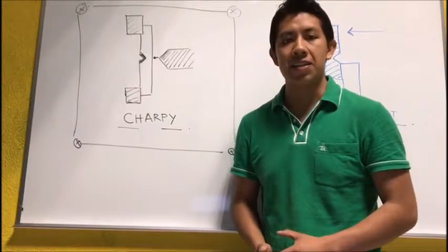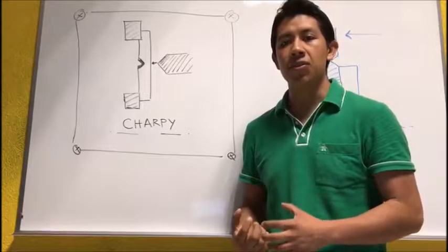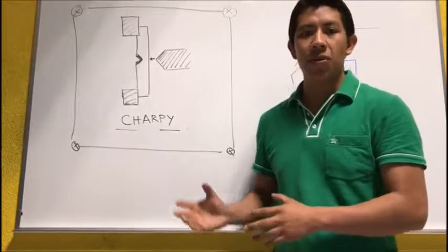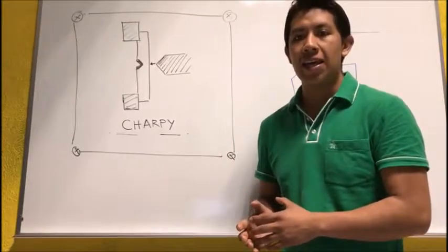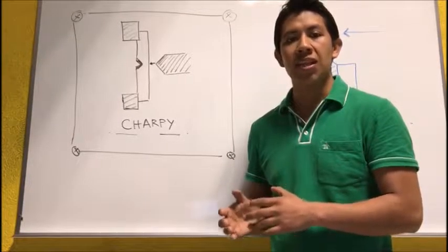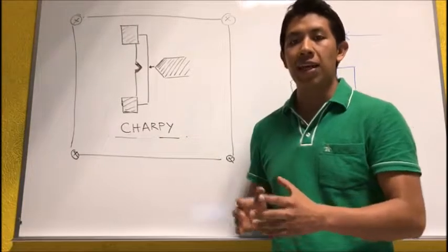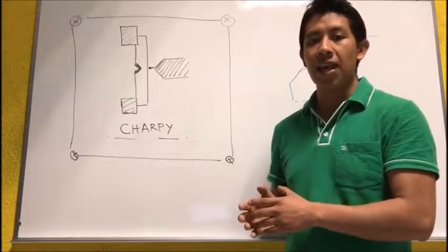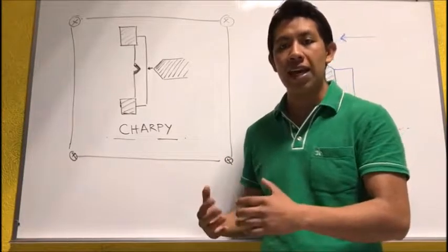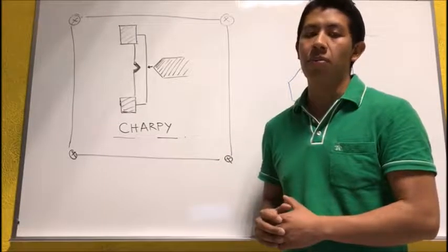The Charpy impact test determines the amount of energy absorbed by a material during fracture. This absorbed energy is a measure of a given material's notch toughness and acts as a tool to study temperature-dependent ductile-brittle transition. It is widely applied in industry since it is easy to prepare and conduct, and results can be obtained quickly and cheaply. The disadvantage is that some results are only comparative.